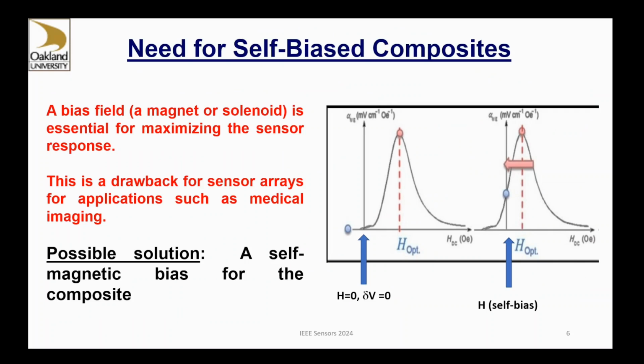So the idea is to detect an AC magnetic field, but we also need a bias field to make sure that we have enough sensitivity. That would lead to a lot of problems for a magnetic field sensor that has to be utilized for biomagnetic imaging, because each sensor element will have its own magnet, leading to significant noise, so the system will lose all its sensitivity. Instead, the idea is to provide a self-biasing field for the ferromagnetic phase. That's what we did. We were able to make a ferromagnetic phase which has self-bias and also very high sensitivity because of strong magnetostriction in the piezomagnetic coefficient.